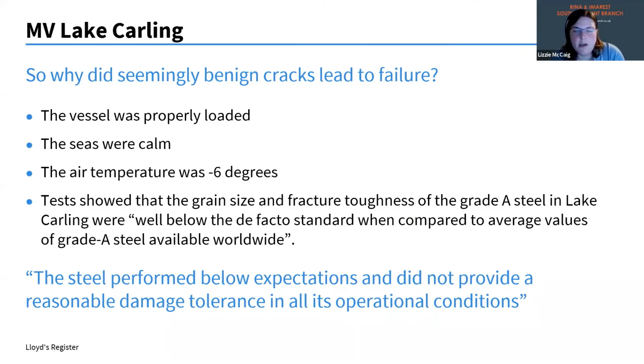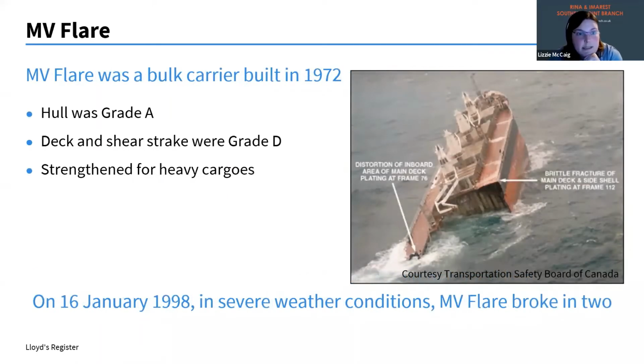grain size of the steel were below, there wasn't an official industry standard at the time, but they were below the average values that you would see for grade A steel at that time. And this is a quote from the accident report. It said, "The steel performed below expectations and did not provide a reasonable damage tolerance in all its operational conditions." So this is a case where the material itself was just poor quality, and that led to the brittle fracture.